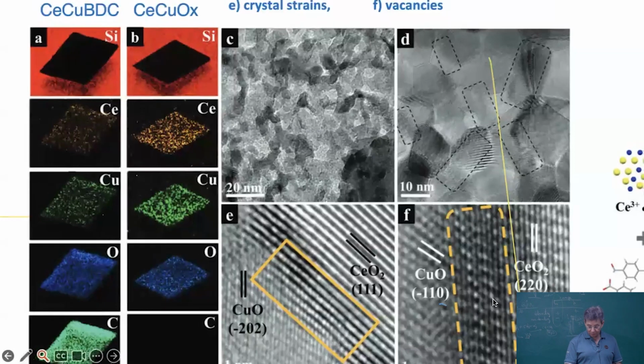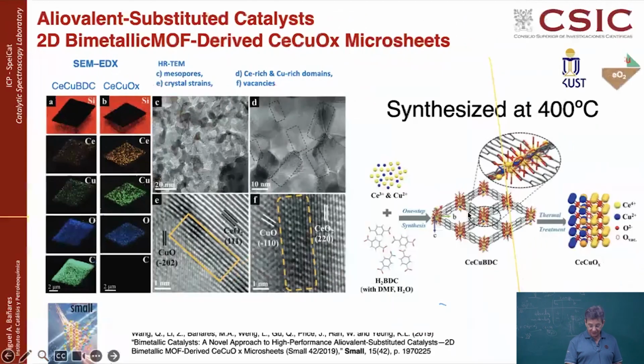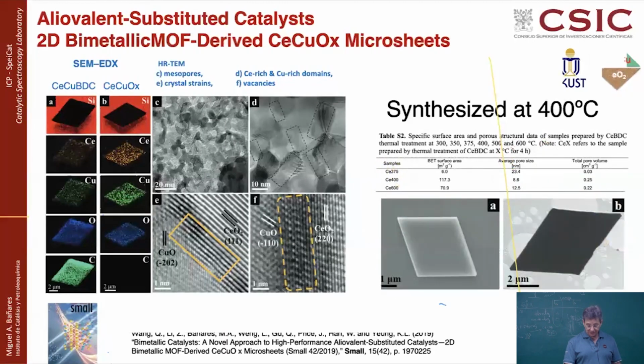Over here it is even more apparent. So basically, the synthesis is something like this: you have this material, and then you do a combustion to get this mixed oxide with a deep entanglement between the copper and the ceria. So this is before, and this is after combustion.